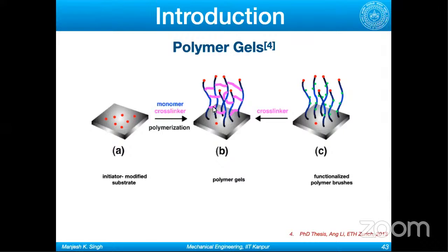The reason why we would like to cross-link the polymers is to increase the modulus. Normally the polymer and solvent alone will have very low modulus, so they will wear off easily. But if you do the cross-linking, you can improve the modulus or stiffness, and so you can reduce the wear. So you have to have a combination, a kind of brush and gel, with optimum cross-linking so that you have low friction and low wear as well. Because if you have a lot of cross-linking, as we will see, the friction will go up.